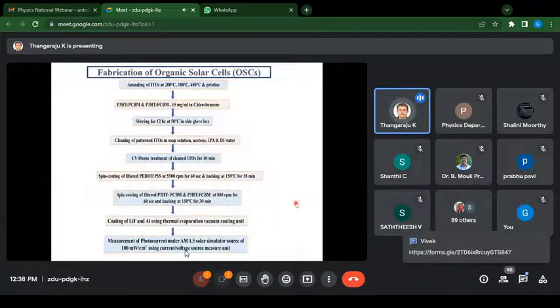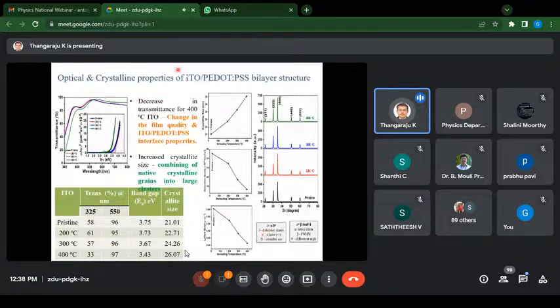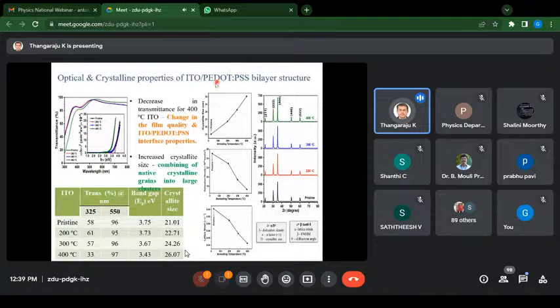So these are the typical steps involved in the fabrication of organic solar cells. We have also found that the combination of annealing of indium tin oxide and using a PEDOT-PSS hole transporting organic layer onto this annealed ITO will improve the solar cell efficiency. So we have fabricated solar cells based on the combination of indium tin oxide and PEDOT-PSS bilayer structure to improve the solar cells. It is observed that the transparency is improved, and the band gap is slightly decreased because of the absorption of this PEDOT-PSS interlayer, a polymer layer. This polymer layer will improve the device efficiency.